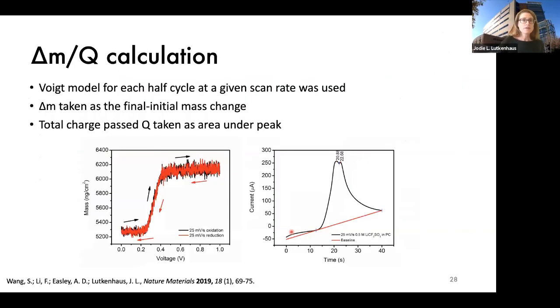Okay, so now we want to calculate delta M over Q. I'd like to tell you about how we do this. We did the Voigt model for a half cycle of a CV. You could do this for an oxidation cycle or a reduction cycle. We plot mass, and we just take the change in mass from these two different plateaus and call that delta M. And then for Q, we take the integral under the peak in the cyclic voltammogram.